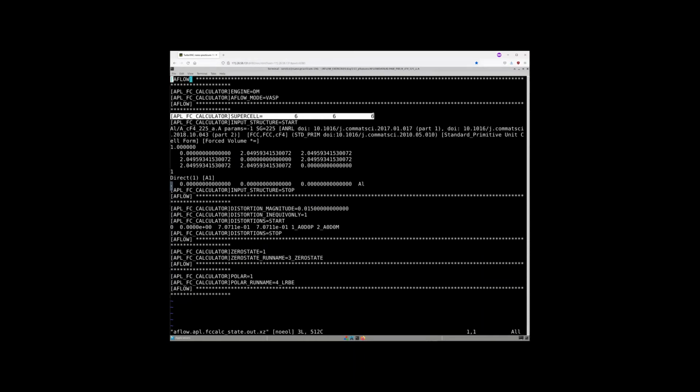I'm not going to go into all the algorithms that we can use to generate them, but here it was a minimum number of atoms. We want a uniform expansion, or as uniform as possible, keeping it as spherical as possible, to fit in this case 175 atoms. That's our default, which often works, but again, you need to test that it actually is enough, or maybe it's too many. And this resulted in a 6x6x6 supercell.